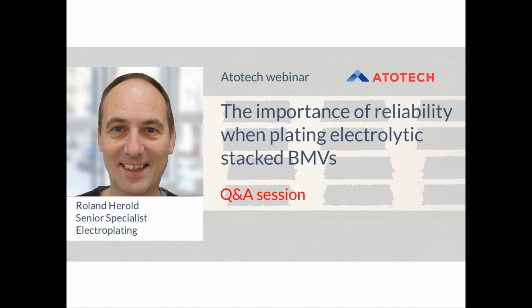For EcoPact, we do not have this problem. Keeping the copper surfaces always free from the polymer, there's no etching required, at least no strong etching. And so the precondition of the target pad after EcoPact is very good to have a very low additive adsorption at the end. And so we have a very good integrity.